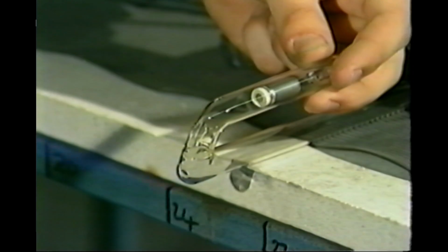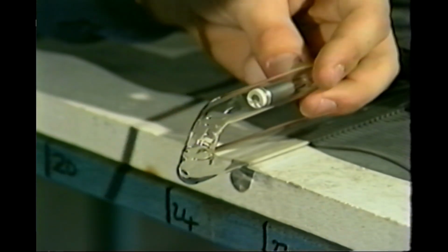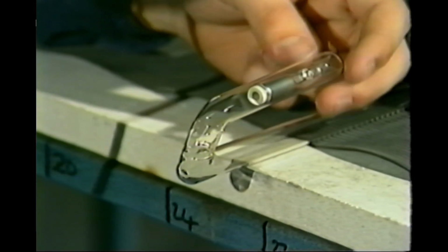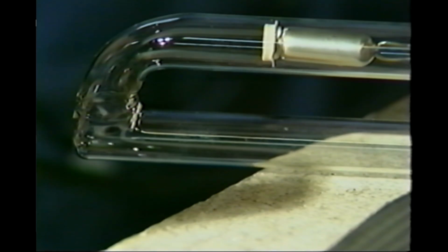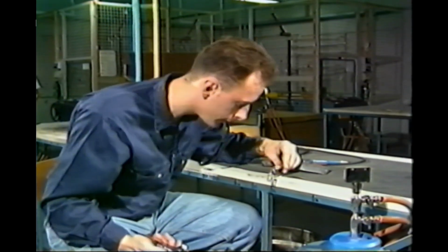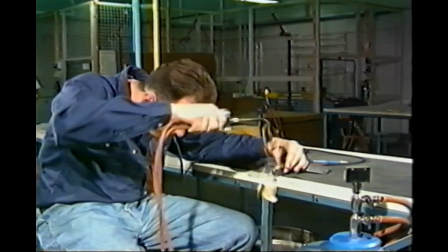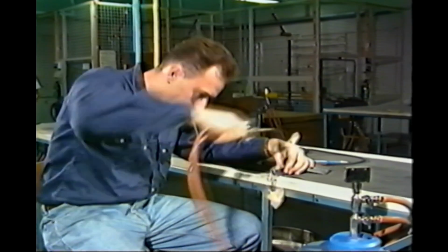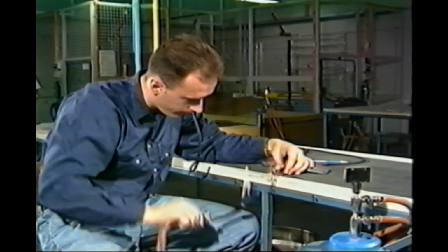Continue the blowing and bending until the electrode is parallel to the tube and the correct glass diameter of the bent area is achieved. The distance between the electrode and the tube should be 1 tube diameter, and the electrode should be parallel to the tube and directly in line when viewed from above. If this is not correct, alignment can be adjusted during annealing.